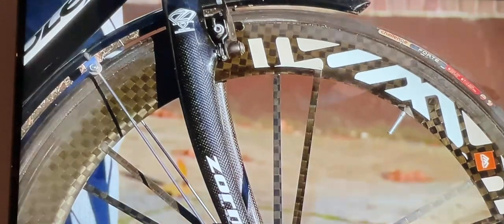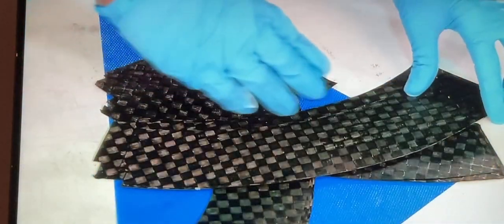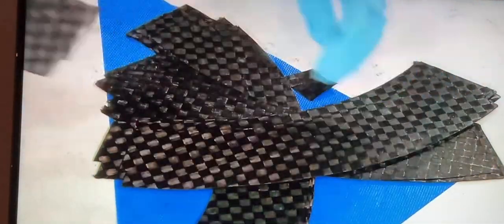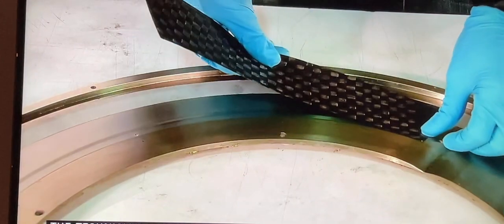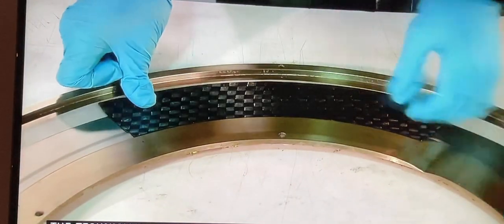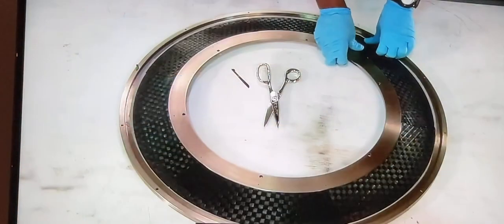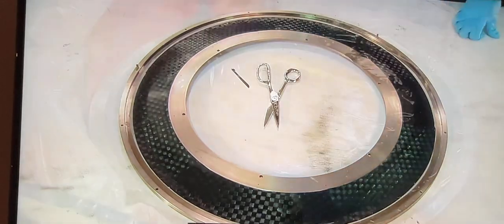They start by cutting carbon fiber into patterns. These arcs are for half of a disc wheel. The technician layers them onto a band of fiberglass in a mold. The fiberglass will provide a good braking surface.